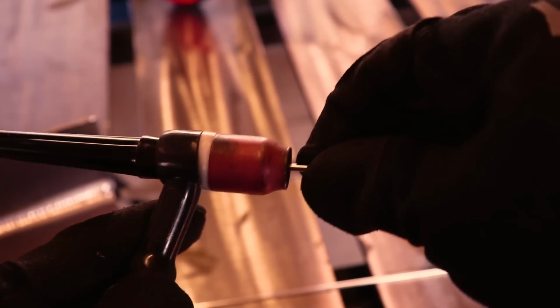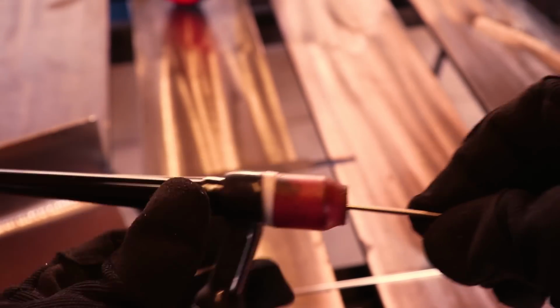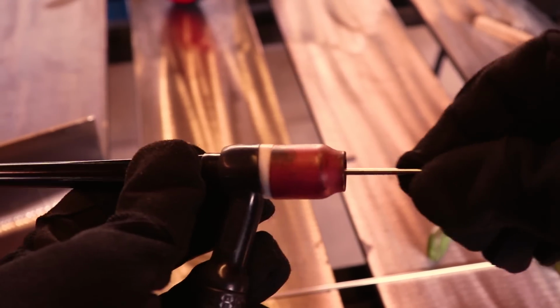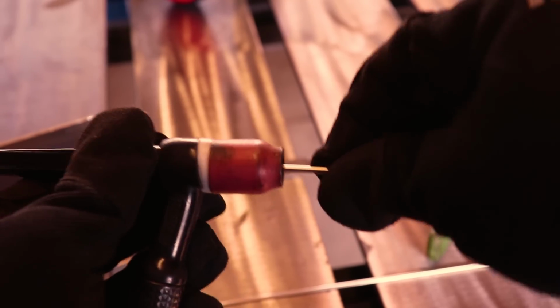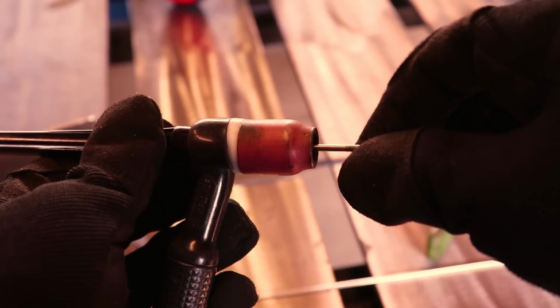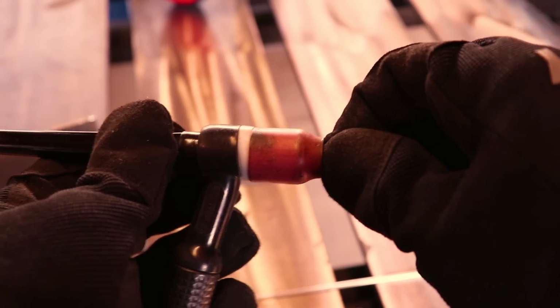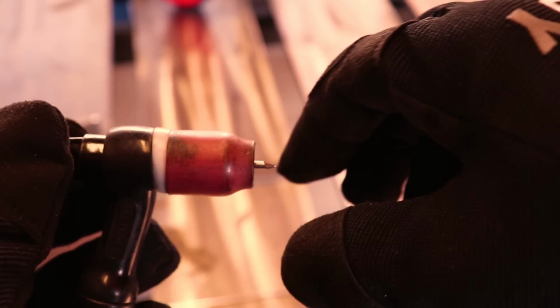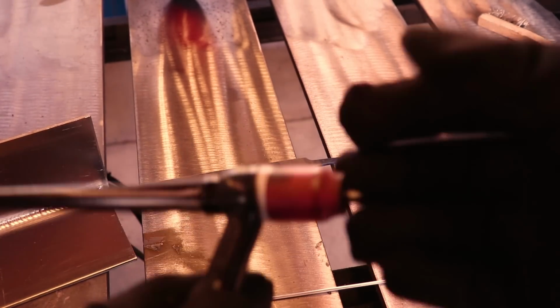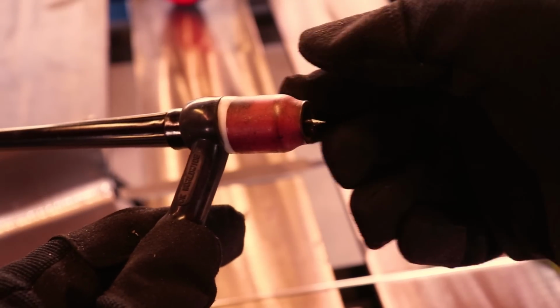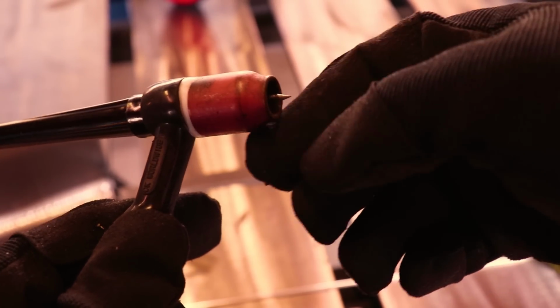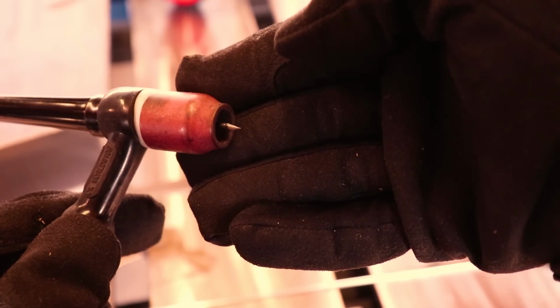Here's a quick tip. If you're having trouble putting your tungsten back in, a lot of times if it's too loose, it won't go in. So just tighten it down slightly until it'll go in, then you're good. So on this, I'm going to keep about a stick out somewhere around there, 1/4 inch or so. Number 7 gas lens, 3/32 tungsten is what I like to run for most things.